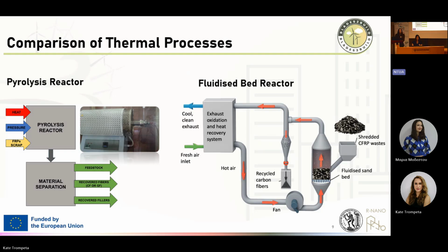The FRP scrap, and this enables the material separation on the recovered fibers, on the recovered fillers, or on the oils that are produced. A fluidized bed reactor is, as you may see here, a more complicated apparatus. It's actually a system including the fluidized bed, which is filled with sand. This is the filling material. There is a feedstock with the shredded CFRP waste. We also use a fan in order to feed the reactor with the hot air.